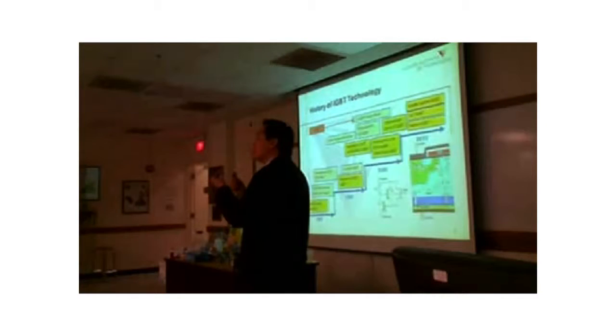And that's everybody's common approach, with one exception. Siemens, now they're called Infineon. The Siemens Semiconductor, before they got spun off as Infineon. They realized epitaxial wafers are super expensive compared to single crystal wafers without epitaxial. They call those float zone wafers. So the only motivation driving them down a different road is the cost of wafers. So they were the only one who did not use the punch-through structure. They use a non-punch-through structure where you have a fairly thick wafer, 400-500 microns thickness, versus 50 micron to 100 microns epi thickness.